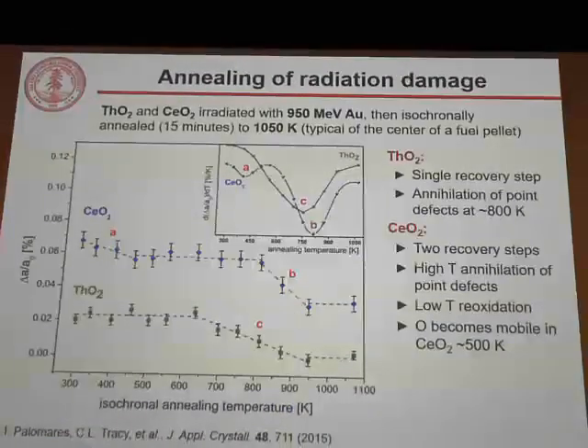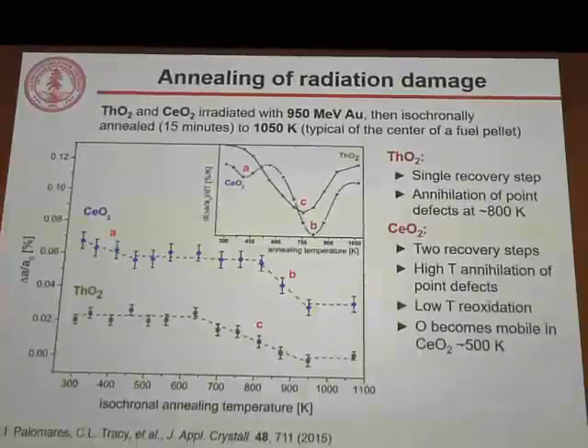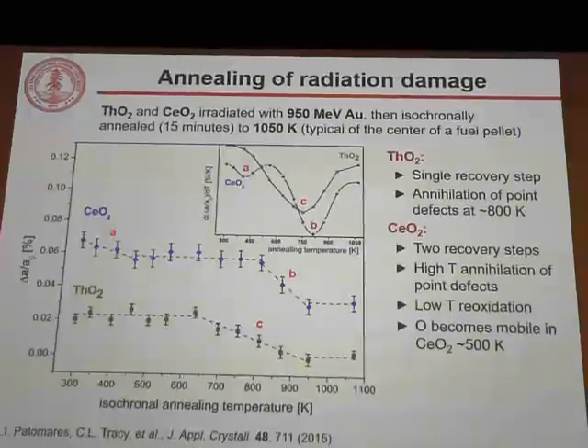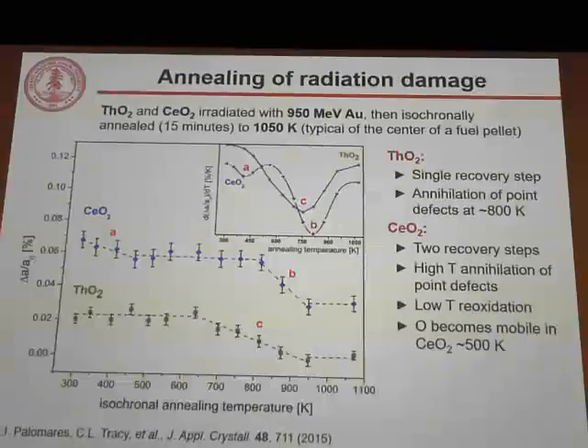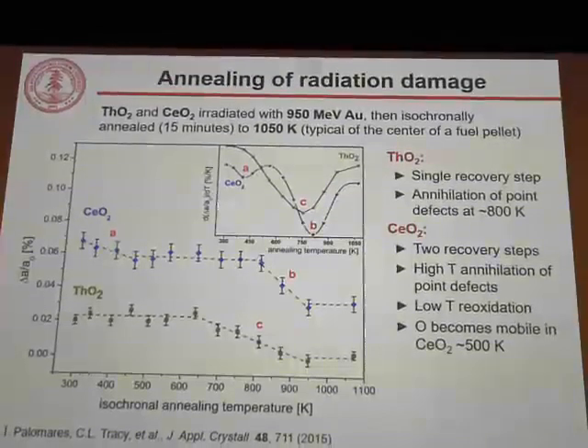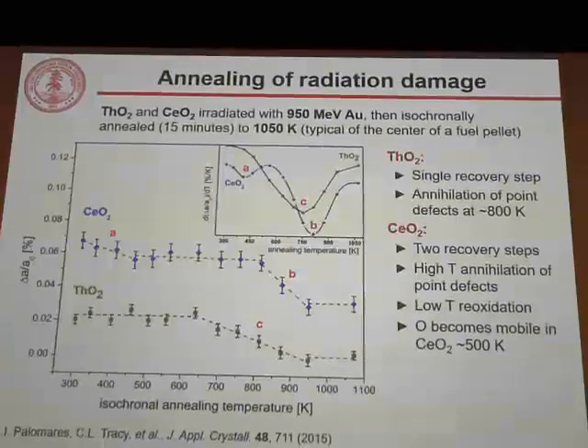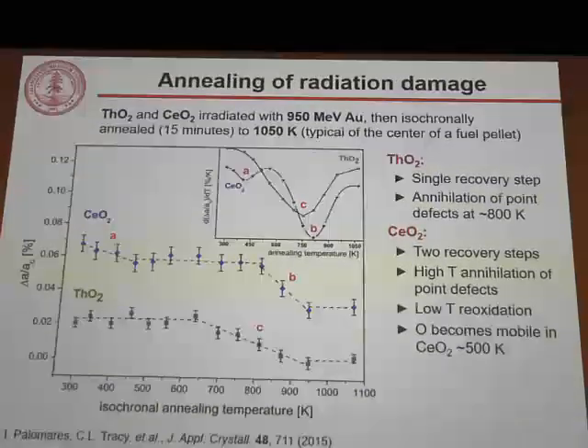I talked about combining extreme environments, so of course an interesting thing now that we've induced radiation damage is to see how it anneals out, how high temperature modifies it. So what we did is annealed irradiated materials up to around 1,000 Kelvin, which is a temperature typical of what you would find at the center line of a fuel pellet. So I show here the change in unit cell parameter after irradiation as a function of annealing temperature.